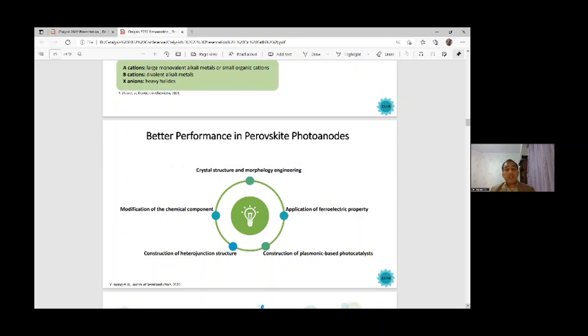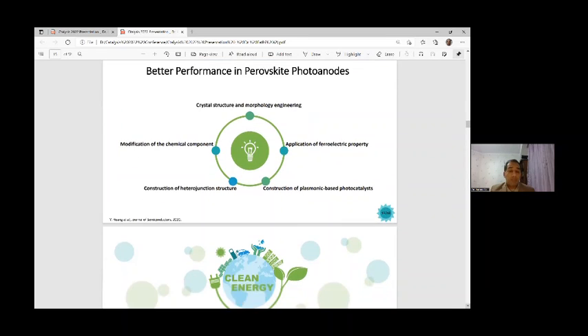For better performance in perovskite photoanodes, in the PEC water splitting systems that utilize perovskite as the photoanode material, we should take the following actions. Crystal structure and morphology engineering is usually required. Modification of the chemical component, construction of the heterojunction structure, application of ferroelectric property, and construction of plasmonic-based photocatalysts. We usually apply the plasmonic behavior of nanoparticles like metallic nanoparticles, Ag nanoparticles, and gold nanoparticles that show plasmonic behavior in order to improve the performance of the system and the light absorption mechanism.